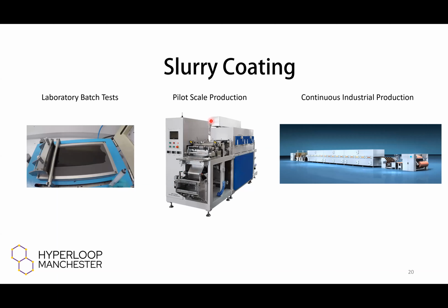A larger scale, a pilot scale version of this is where you'd have a roll-to-roll system feeding through. There's an oven at the back here, and the coating, sort of a gravure coating head here, which is again similar to a gap applicator. It's just got a thin gap that you're passing the material through, and you'd be adding slurry into this and you'd run it until the foil runs out, and the ovens are kept at like 60 degrees. You'd be looking to get, I don't know, only 5 meters per minute of production out of this, like 5 meters of coating per minute.